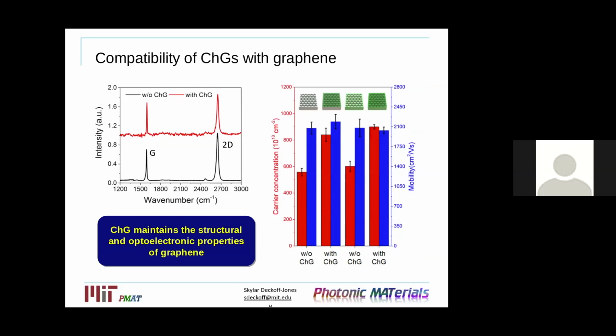So first, I want to give some background to show my previous comment that the chalcogenide glasses can be deposited on 2D materials without damage. So on the left, we have a Raman spectra of graphene with and without our chalcogenide glass. And we see that after deposition of our chalcogenide glass, we don't see an appearance of a defect peak. So we see the Raman spectra is still preserved.